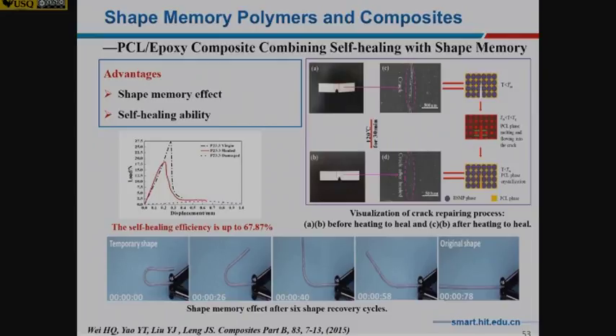We also make some self-healing composite with shape memory property together. For shape memory, you can see from the bottle and the graph that the shape can recover, but not only shape recovery. We put some thermoplastic polymer inside, which can heal some cracks. You can see the crack there, and afterward, the crack can disappear. The self-healing efficiency is about 70%. That means the polymer not only can recover its shape, but can also heal some cracks.